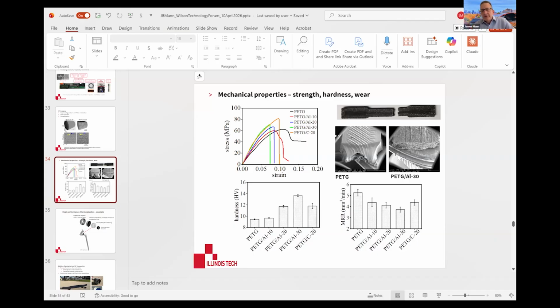And then an interesting artifact of the tensile testing is that the PET-G goes from a ductile failure type of mode to a brittle failure mode. That's what those images are from the SEM. And then hardness, you can see with increasing the fiber percent by weight content, the hardness increases and actually exceeds that significantly over carbon fiber. And then the wear resistance, the actual wear behavior of the 30% by weight aluminum fiber actually outperforms carbon fiber.